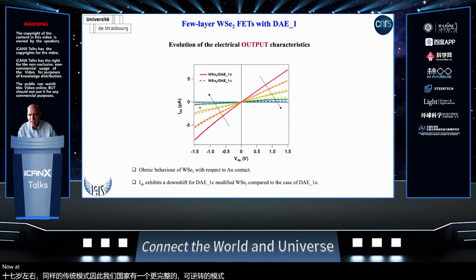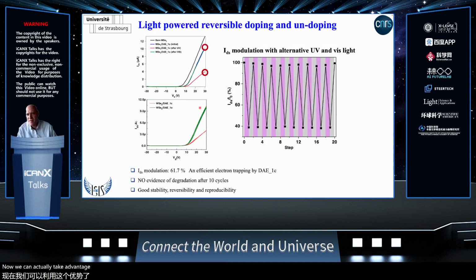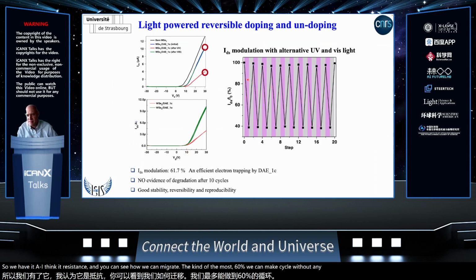Now, we can actually take advantage of the fact that the diarylethene is a very robust photoswitch, and actually the two states are thermodynamically stable. So we have a high fatigue resistance. And you can see how we can modulate the current about 60%. We can make cycles without any fatigue.